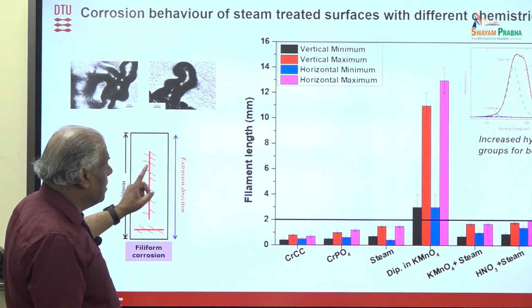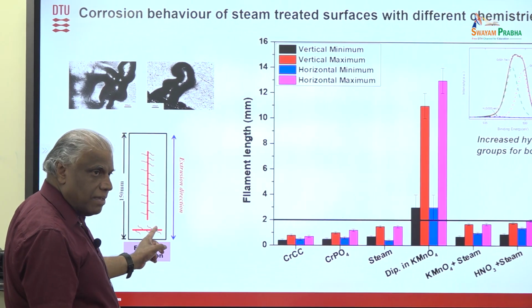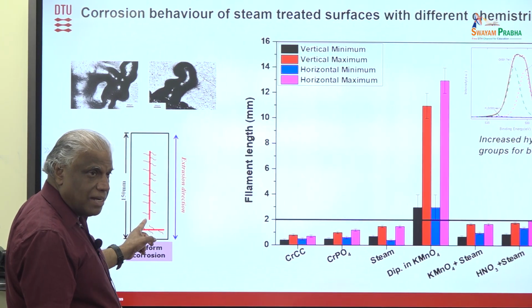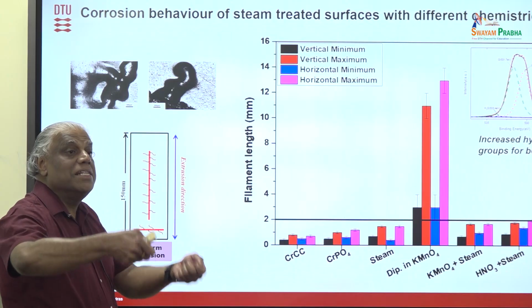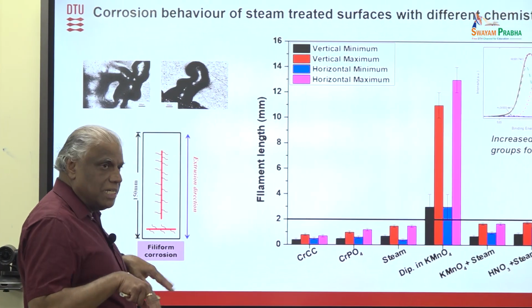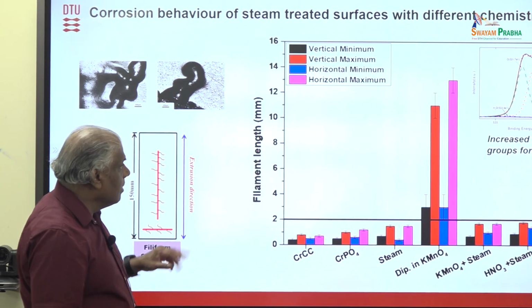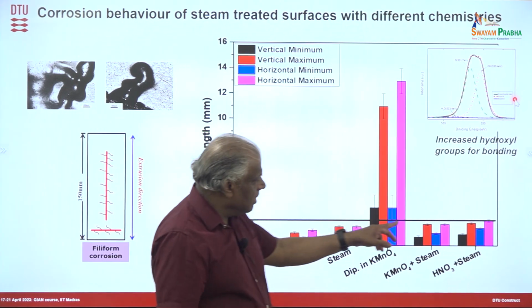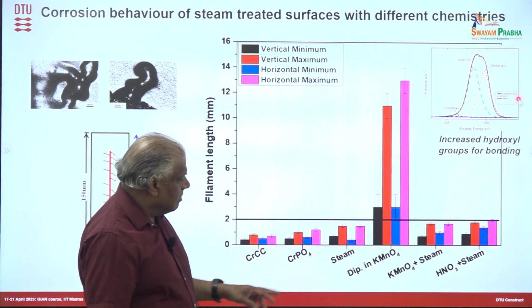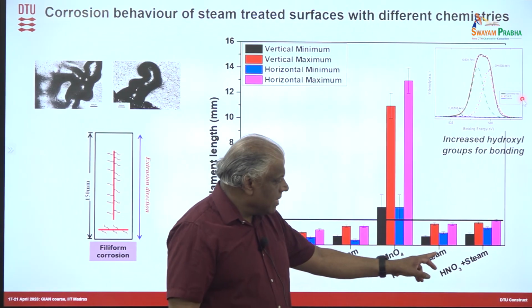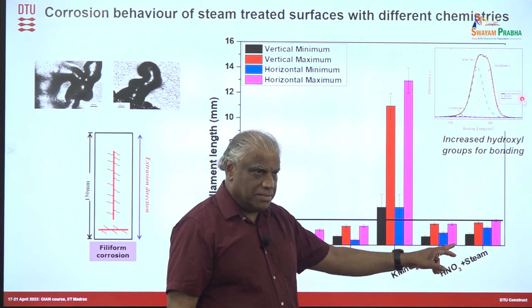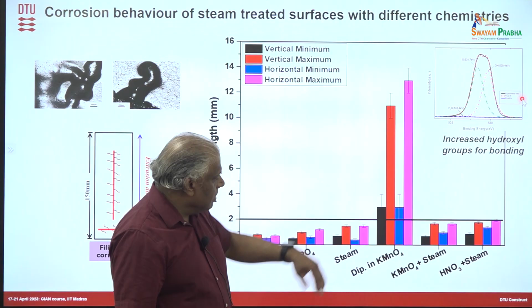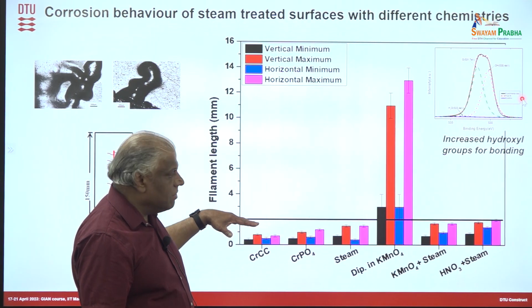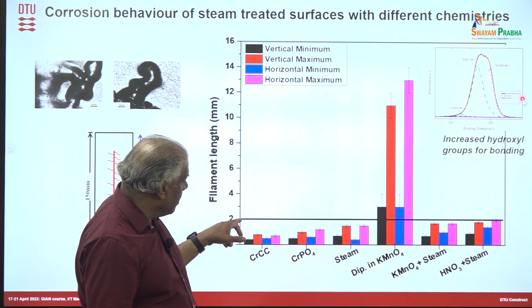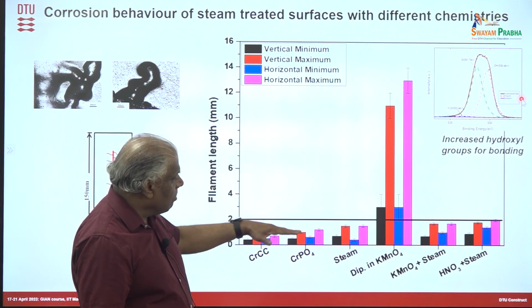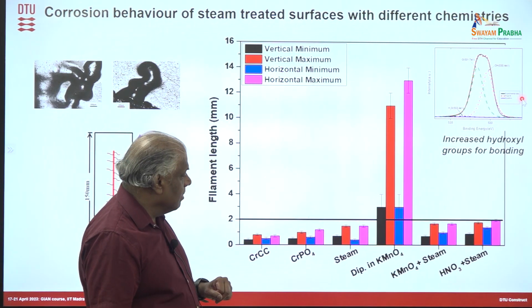Here what we do is there is a specific test for the filiform. You scratch it this way, and then you put some hydrochloric acid, if I remember correctly, so that some chloride is introduced. Then you put it in a humidity chamber. In the humidity chamber, the humidity will make this chloride penetrate and the corrosion occur. Then you measure the filament length. That's what you see here. So when you do that, you can see that steam-based treatment, potassium permanganate and steam, nitric acid and steam, we can do many chemistries. And you can see that all of them are within the limit. This is a standard which they want. The filament length has to be below 2 with that testing. So all of them were good with that from the point of view of our coating.